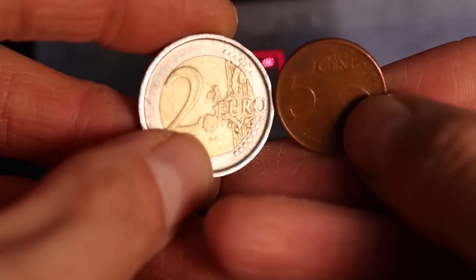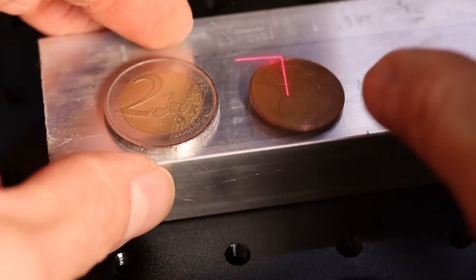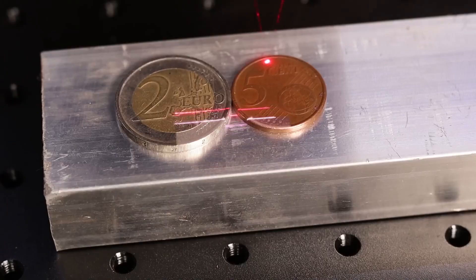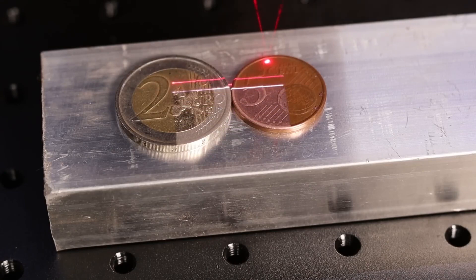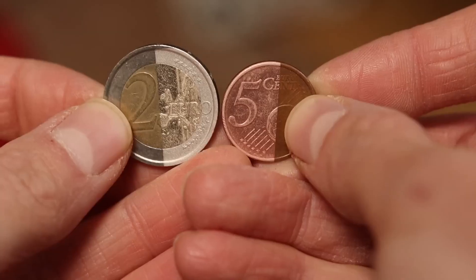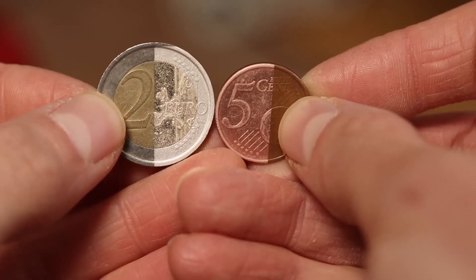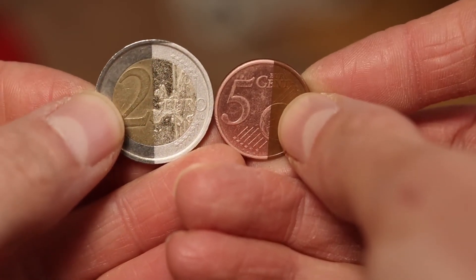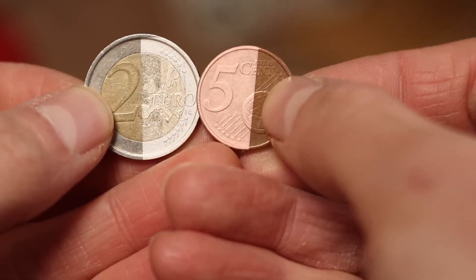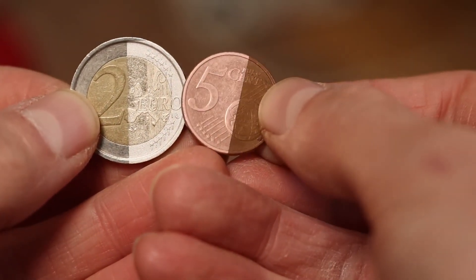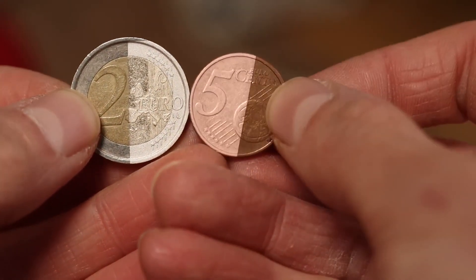High speed, low power and high frequency produce a polishing effect. You can use this effect for cleaning dirty coins or removing rust. If the power is set low enough, it does not mark the metal, it only vaporizes the dirt.